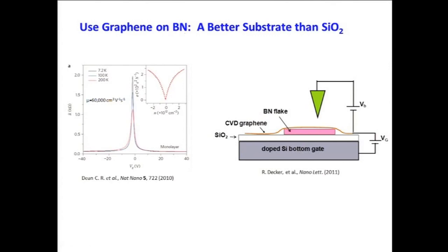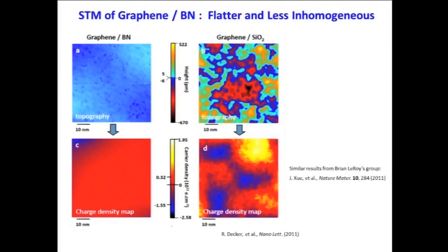And so we were inspired by this great result to try this ourselves. We built some devices in this fashion. We put boron nitride flakes on silicon oxide, and we took CVD graphene and put it over, and then we stuck it into our scanning tunneling microscope. Alex Zettl's group also helped us to fabricate these devices. And so we looked at those devices with STM, and it turned out that they looked really great.